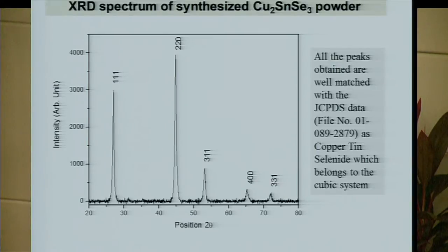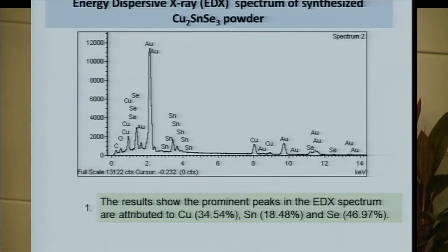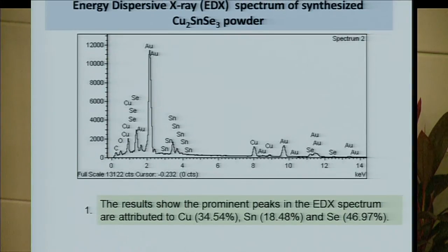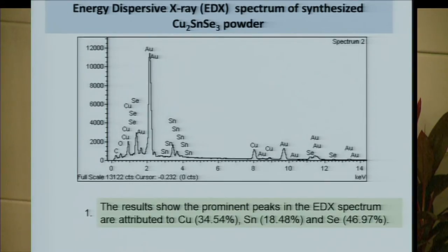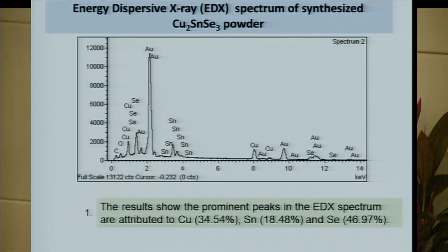So once we have identified the materials using X-ray diffraction, then we would like to know whether it contains the necessary formulation or the stoichiometric ratio of the compound that we intend to synthesize. And so we use what we call the energy dispersive X-ray to look at the material. So this is an elemental technique which would give us what kind of elements are in the material and what are their proportions in relation to one another. So the results from energy dispersive X-ray, or we usually call it EDX, shows that the proportion of copper and tin and selenium was at the right stoichiometric ratio that we intended to have.